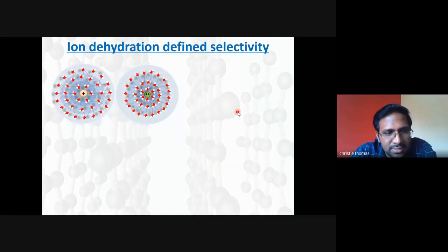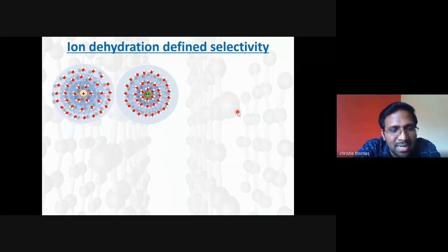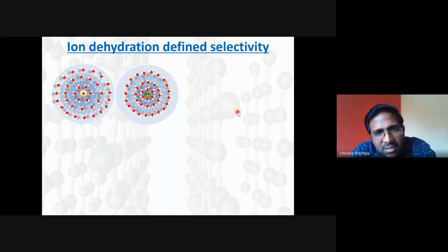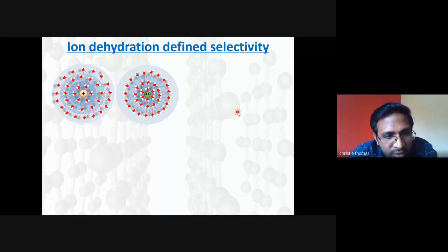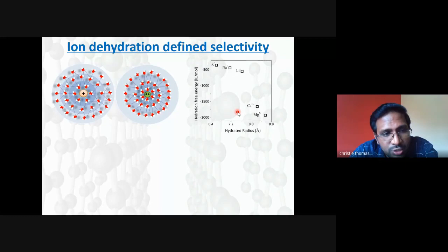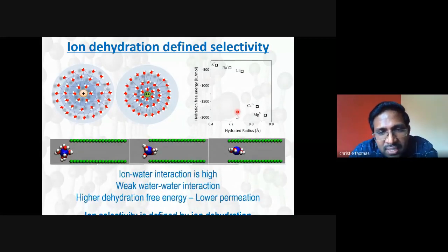Why is it so? You know that in bulk solution, and chemistry students know this very well, water molecules stabilize ions by forming a concentric hydration shell. Now, for an ion to enter a channel with a capillary size less than its diameter, some water molecules must be removed from the hydration shell, or it will get squeezed. You can see a simulation here, where the water molecules get squeezed to go through.